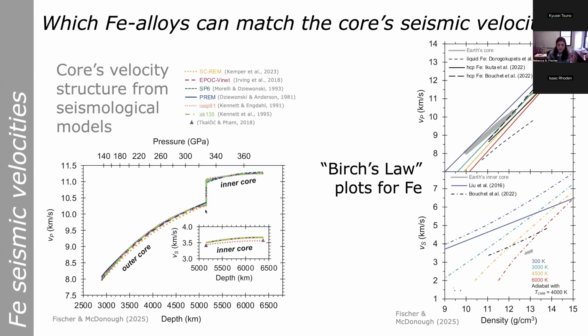And then we can compare it first to the velocities for pure iron. So these are so-called Birch's law plots showing velocity versus density, with VP on the top panel and VS on the bottom panel. In both cases, the gray shaded regions are the range of velocities reported in these different seismic studies. The black curves are velocities for pure iron calculated along an adiabat at core conditions. And the colored lines are all isotherms for pure iron.